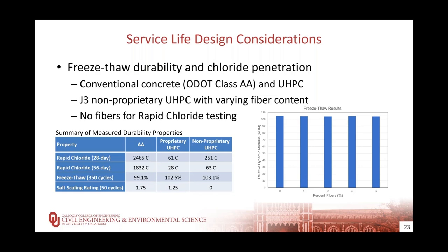The freeze-thaw resistance for the Class AA concrete was very good in terms of relative dynamic modulus, but both UHPC mixes with 2% steel fibers had an increase in dynamic modulus over time. The same was true when the fiber content was varied for the non-proprietary mix, with each fiber percentage exhibiting excellent performance. These results indicated that the fiber content had little impact on the freeze-thaw resistance of the material itself.